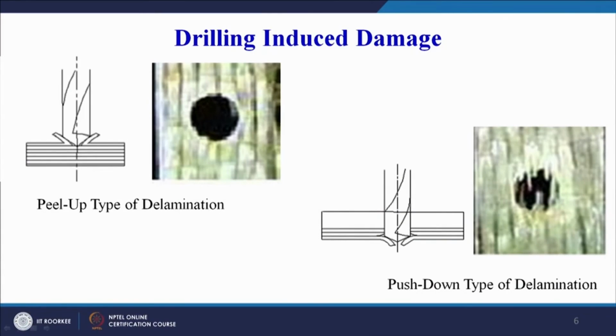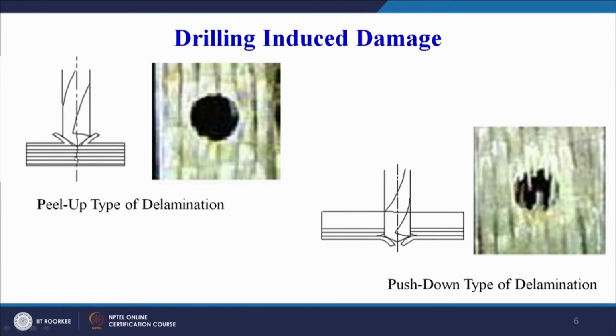There you can see the drilling induced damage. So delamination, basically you can see there is a peel up type of delamination when the drill just starts to enter the laminate. So this is the laminate. When the drill starts to enter the laminate, the top layers try to peel up, or the drill subjects these plies or the top layers or the top laminae to the peeling effect, and the layers debond from their bottom layers and they peel up along with the drill, and this is called the peeling up type of delamination.